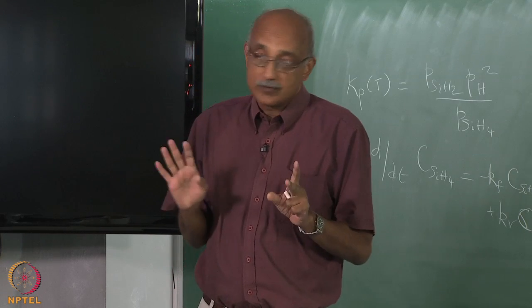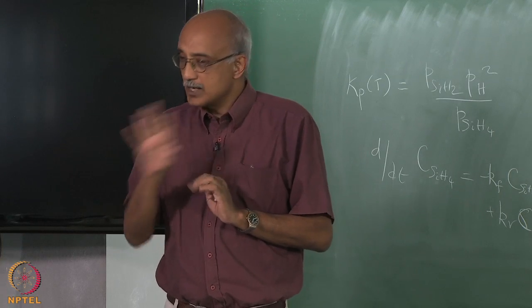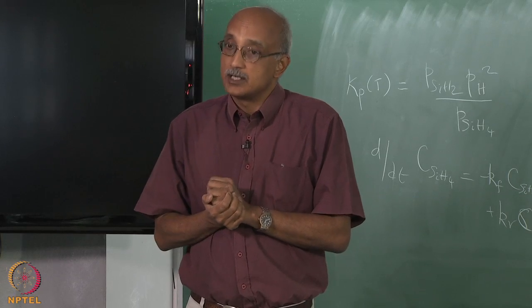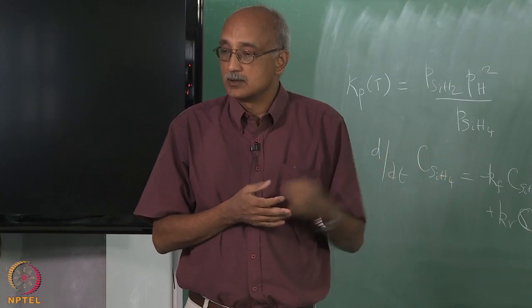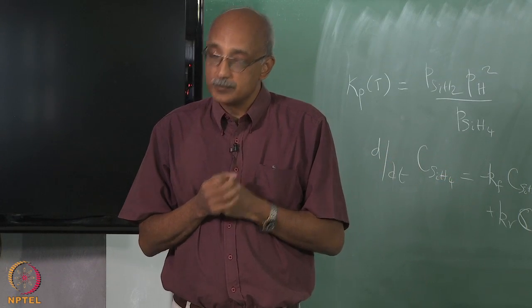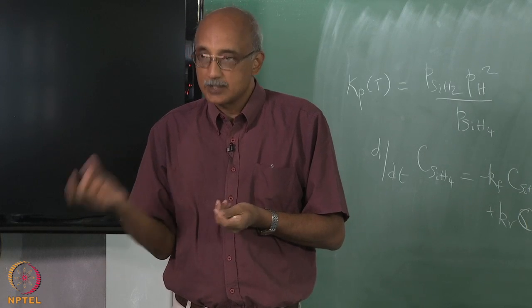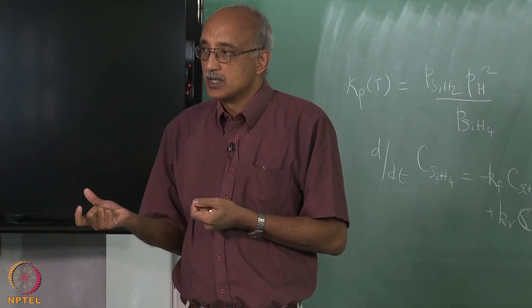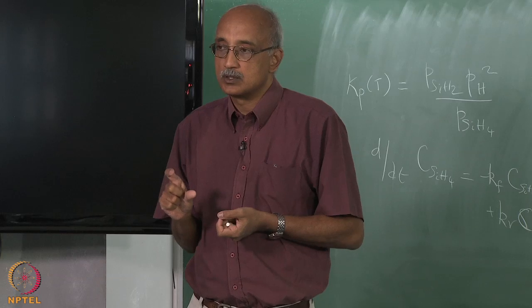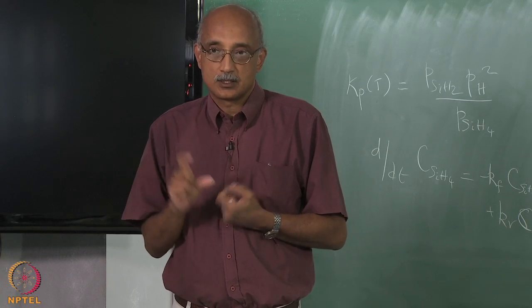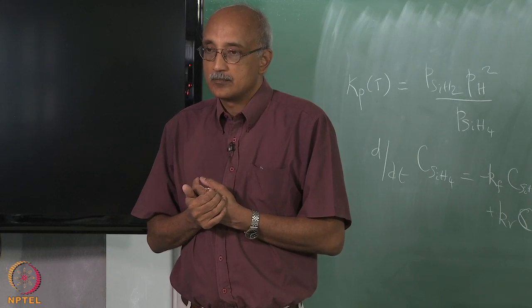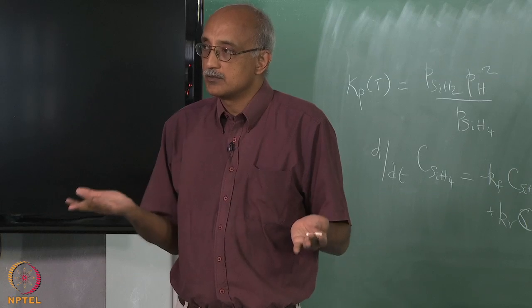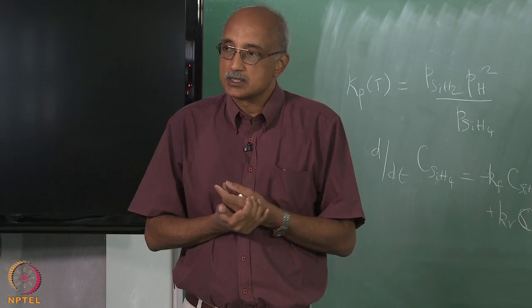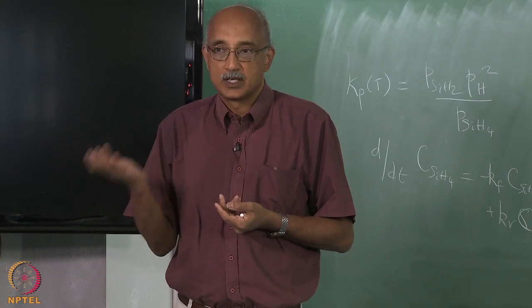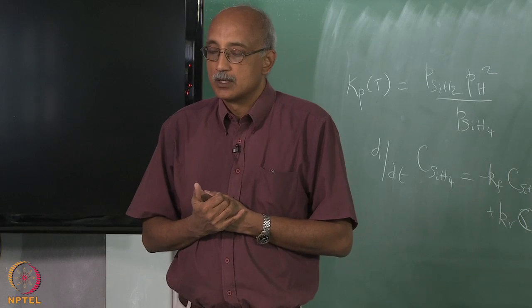Now, all that we have discussed so far are reactions happening in the gas phase. And even though they are quite complicated, they are actually quite simple when you compare them to the reactions that are going to be taking place on the surface, because even less is known about heterogeneous chemical reactions when you have such a multiplicity of gas phase species coming in contact with an energized substrate.